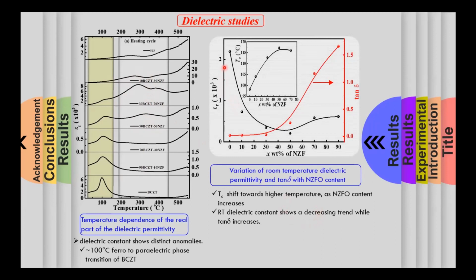Here we see the variation of the room temperature permittivity and the loss tangent with the different weight fraction of nickel zinc ferrite. Quite obviously, when the piezoelectric phase is decreasing, the permittivity will decrease. And the reason for the increase in the loss tangent with increasing nickel zinc ferrite phase is basically because the magnetic phase is relatively conducting as compared to the piezoelectric phase.